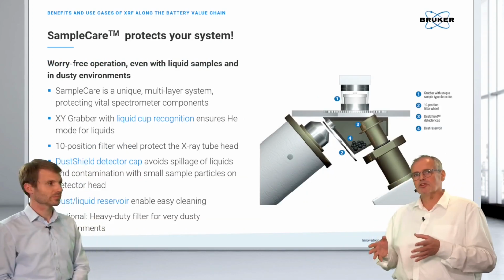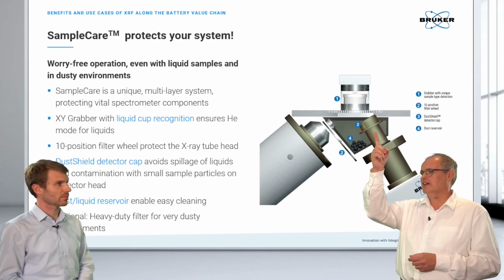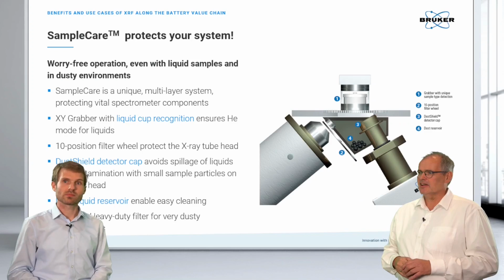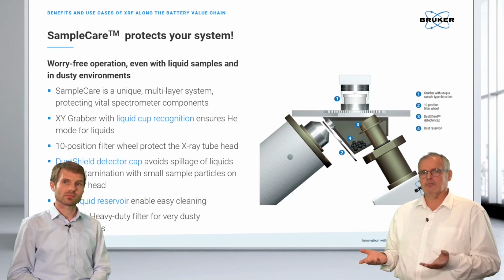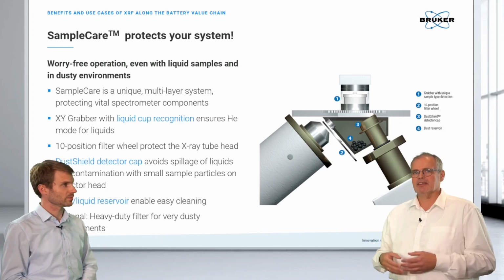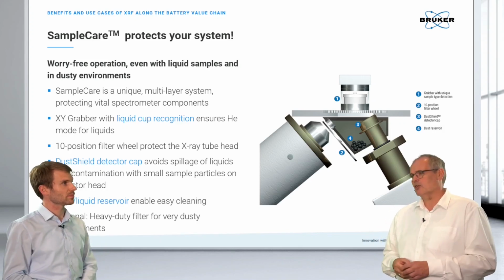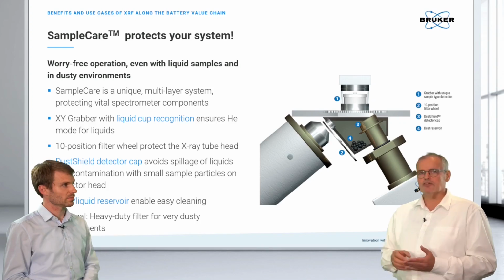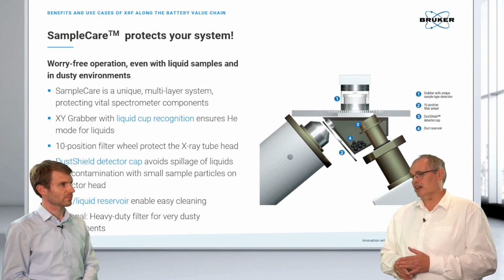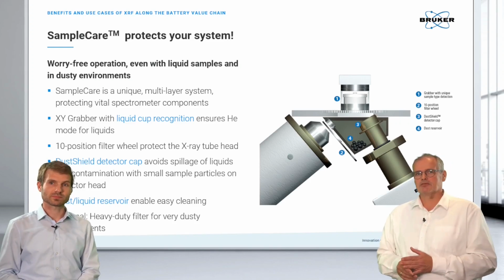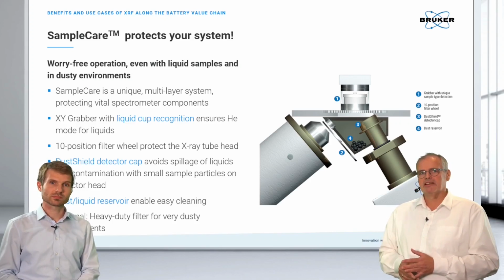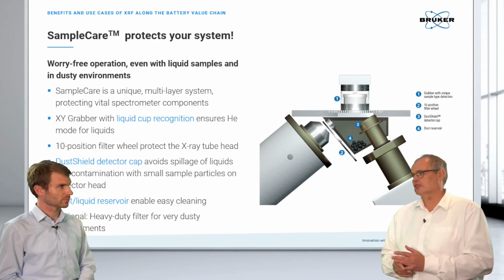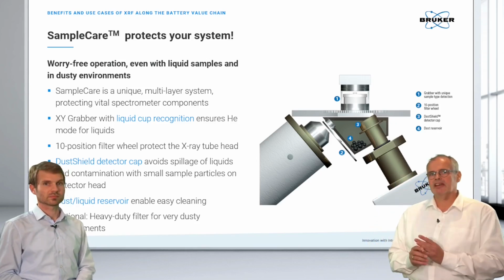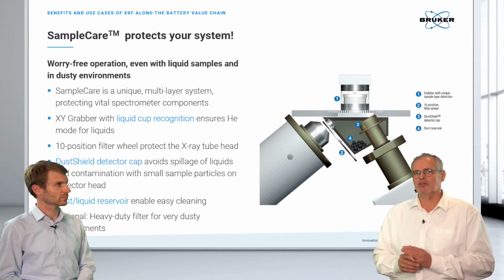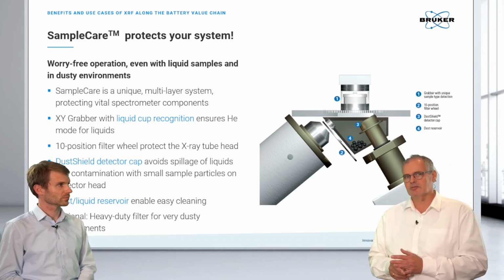And when we look inside, we see here the sample. Of course, it's a cup with a thin foil on the bottom. It may happen that the foil breaks and the powder is released. Therefore, we need to avoid contamination of the X-ray tube. This is a pretty expensive component, so the S2 Puma has a filter wheel in front of the X-ray tube, and there is a filter to protect the X-ray tube head. So at the point of breakage of the foil, the powder will not enter and damage the X-ray tube itself.